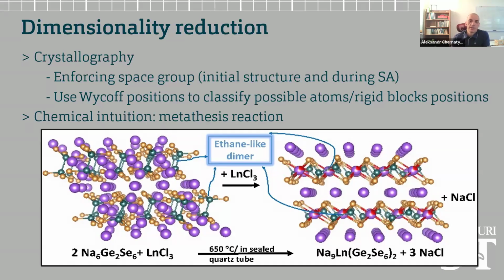And what you see here is, on the left, maybe I can use the mouse. So on the left here, we can see that I have complex chalcogenides, a sodium, germanium, selenium compound. And it has this fairly complicated structure, as you can see. As we look at this, we can notice that the germanium, selenium parts of this compound form this dumbbell-like structure. It is a dimer which forms by a germanium-germanium bond with the selenium sticking out at its points.